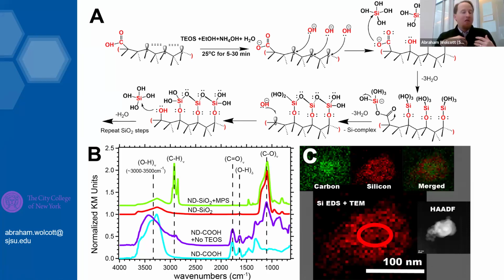And so depending on the robustness, imagine this, Olga, we do our silica chemistry and then we anneal the sample. We make them more crystalline, less amorphous. And if they're crystalline, they should be more robust against dissolution. They shouldn't go back towards tetrahydroxysilane. They should stay with their SiO2 bonds. We've never pursued that. I've thought about it for years. Let's just take silica coated, do a high temperature anneal. You could do it in nitrogen, or in oxygen or open air conditions, and then do the remaining portion of your chemistry to decorate your polyethylene glycols and your amines and everything else that you need. But you would harden the shell, get the shell crystalline.